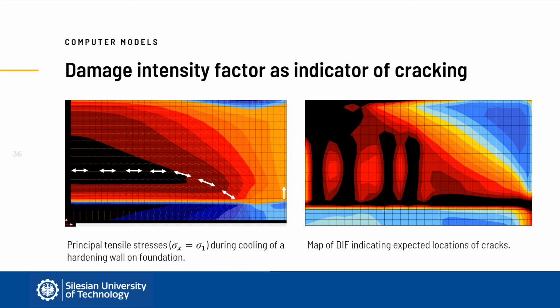Black color means that the damage intensity factor is equal to 1, which in this case is equivalent with reaching tensile strength. Based on the philosophy of the smeared crack image, we can deduce that splitting cracks are formed in the black areas. It is possible to follow their direction of propagation and opening. The crack is formed in the direction perpendicular to the principal tensile stress. That is why we can expect vertical cracks in the central part of the wall, which tend to lean down towards the free ends of the wall, and a disjoining crack is formed at the end of the wall foundation joint.